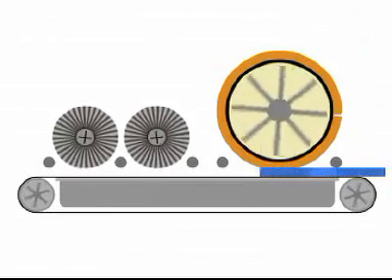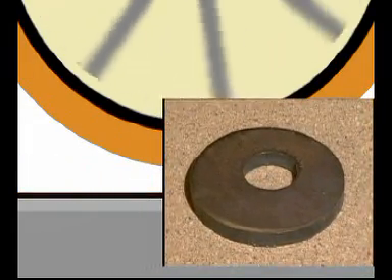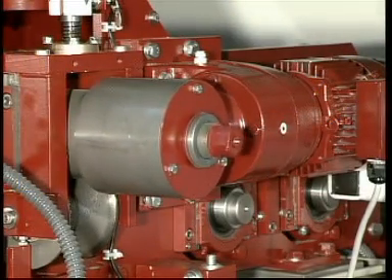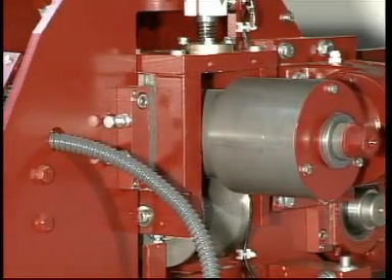How is this possible? The soft backing of the deburring cylinder applies increased pressure on the edges regardless of their orientation, because the rubber foam expands where the abrasive is not supported adjacent to the edge. This causes the abrasive to mold around the edge. On the surface, the opposite effect takes place. The soft foam easily compresses, distributing the grinding pressure to a larger surface. This is combined with the oscillation of the deburring cylinder at high frequency, ensuring an extremely even wear of the abrasive.